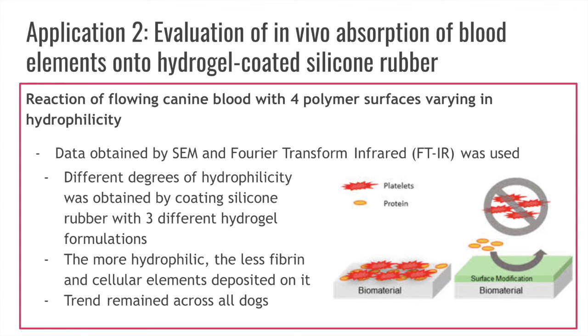Different degrees of hydrophilicity were obtained by coating silicone rubber with three different hydrogel formulations. These materials were used as femoral artery to vein shunts and removed after 15 minutes. They were then analyzed through SEM and FTIR, which includes scanning the samples with infrared light to observe the chemical properties. From the SEM micrographs and the FTIR spectra, the more hydrophilic the hydrogel surface, the less fibrin and cellular elements deposit on it. This trend remained similar across all dogs. There is also considerable variation in thrombus deposition, which is likely due to the progressive thrombus buildup and embolization.